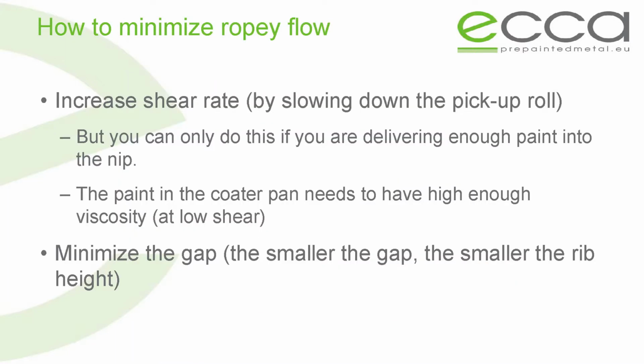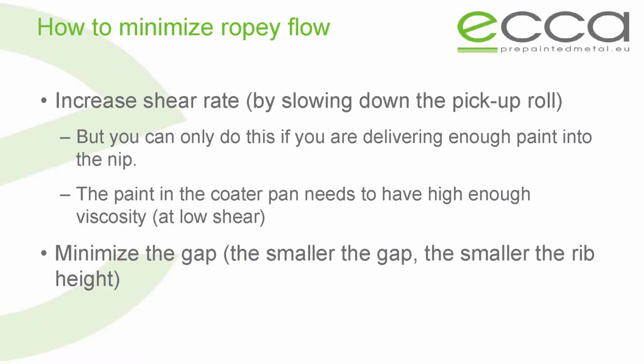But I would say that from my own personal experience, increasing the shear rate solves a lot of these issues. And the only way you can really increase the shear rate on a coil line is to run the pickup roll more slowly. And again, I'll discuss a little bit more of this in detail when I tell you about my perfectly bad experiment.